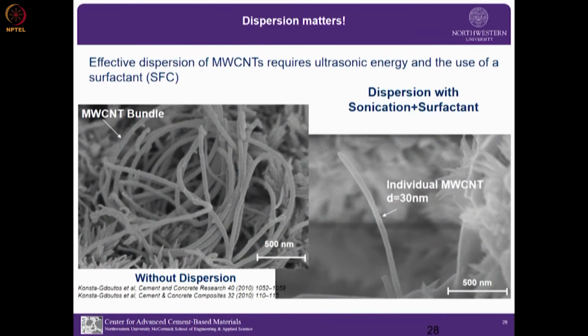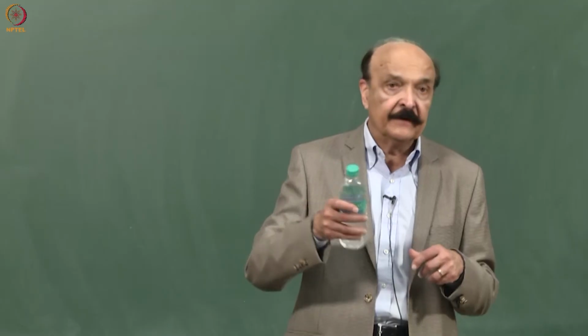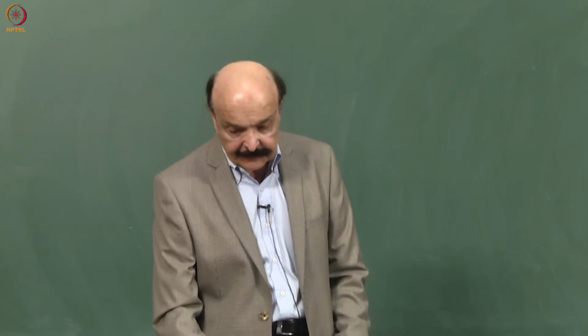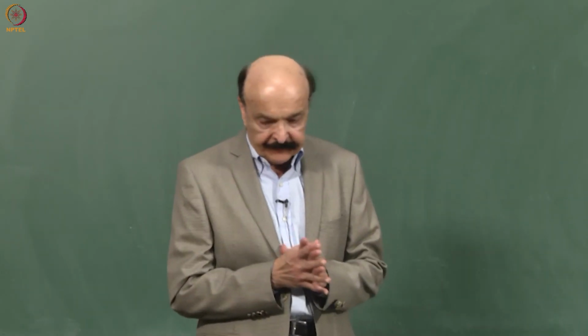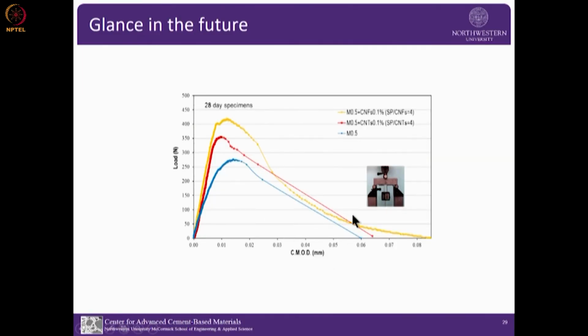So the idea with carbon nanotube reinforcement is not like conventional reinforcement. You have an aqueous solution where, in the factory, you have ultrasonication and surfactant, and then you just use that, similar to superplasticizer. So that's a different way of processing. I want to show you some results with carbon nanotubes. These are fracture tests, on mortar specimens with water to cement ratio 0.5, and these are 0.1%. If you look at carbon nanofiber, for example, we have substantially improved, almost double, the fracture strength, while also maintaining a very good post-peak response.